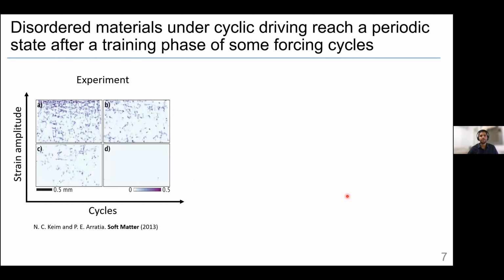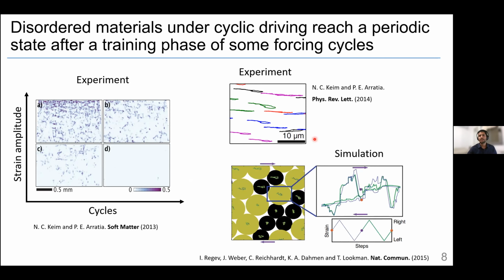What we see in experiments and simulations is that under cyclic driving, amorphous solids reach some kind of a periodic state after some cycles. You can see that here in this example: in blue, you see the particles that change position after the last cycle. For low strain amplitudes, after some cycles, almost all the particles return to their original position. When you increase the strain amplitude, you need more cycles. So here you still have particles that change location, but if you increase the number of cycles, you can get to this periodic state.